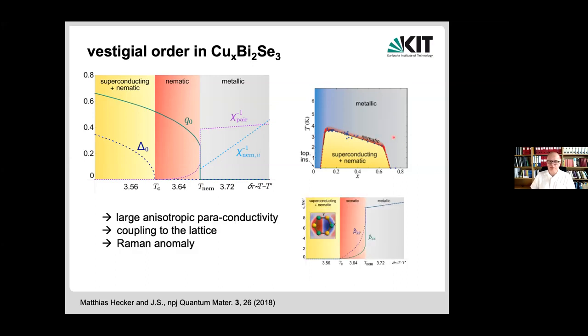One implication, maybe I'm just listing one, is that because of the increased fluctuations, there should be paraconductivity that should even be anisotropic in the system in that intermediate regime, that is much larger than what you would expect in the high temperature non-nematic state. Truly, what changes here is a condensation of fluctuations.